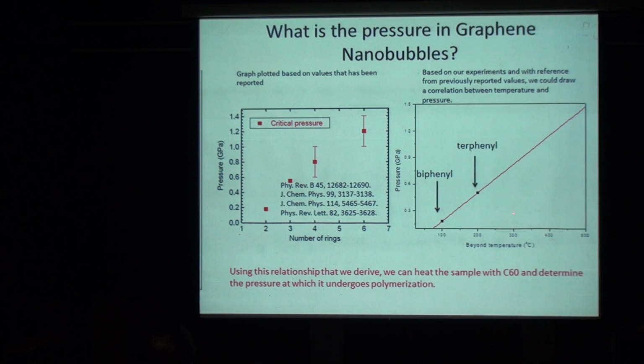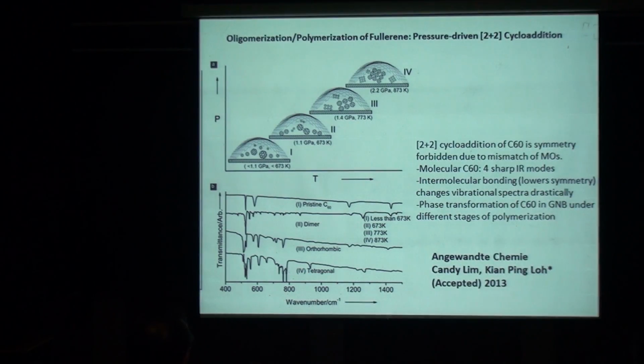So now we know when we heat up to about 100 degrees Celsius, the pressure inside the bubble is about 0.3, at 200 it is about 0.5, and so on. Once you go beyond 400 degrees Celsius, you're already in a gigapascal regime for the nanobubble. The pressure inside is as high as gigapascal, which means that it's a totally different regime from what we are experiencing normally. You can perform chemistry that you normally don't perform using test tubes and beakers. This is high pressure, high temperature chemistry.